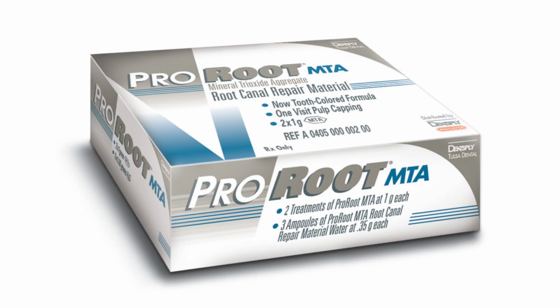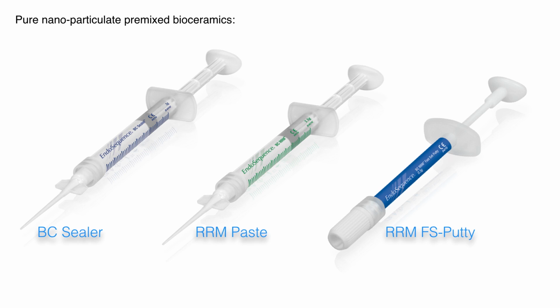Of course, the particle size of MTA was very large, and the handling properties of the MTA were not quite as great because you would mix it up and it would turn into mud, and then applying it to the site always required additional armamentarium, so it was difficult. Plus, because of the particle size, it wasn't really available for the sealer material. And this all changed in 2007 and 2008 when the nanoparticulate bioceramic material became available.